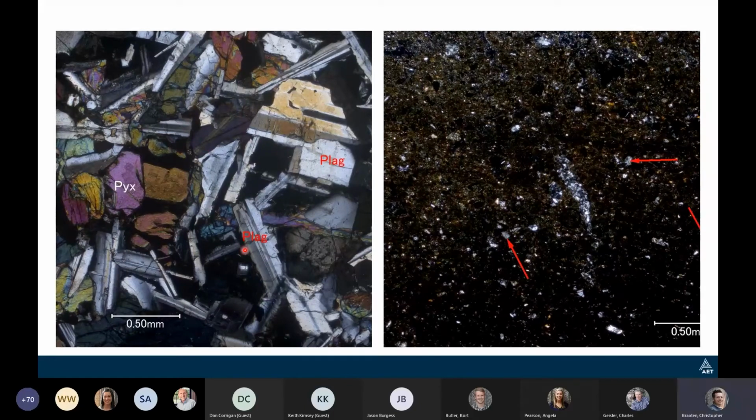Well, as I was digging further into the sample, I started finding all these same color, dark black particles, but they're all rounded edges, dull, earthy looking, and they were soft. So we made a thin section of that, and this is what it was. It's basically like a mud rock with some detrital silt grains in there.